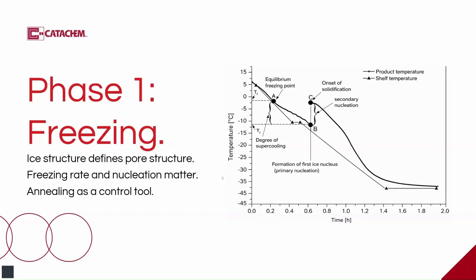At Catachem, we treat freezing as a design step, not a checkbox. As a solution freezes, the unfrozen liquid concentrates. The pH can change dramatically. Cryoprotectants can separate from proteins, so the same proteins can freeze under different conditions. A good freeze cycle is designed to protect the weakest protein and prevent osmotic shock. For vials, we can achieve uniform shelf freezing and map behavior with product probes. For trays, we focus on fill depth and thermal gradients. And for sensitive formulations, we evaluate whether controlled nucleation or annealing improves outcomes.